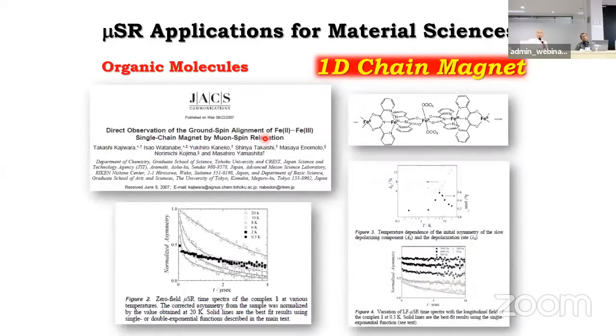So this one is also the first report to show an unordered state. That means muon is easy to pick up the ordered state. So this one, a very quick measurement. I measured 13 data points within half a day, then published this paper in JACS Communications. JACS Communications is almost the number one journal in chemistry. Impact factor is more than 10.